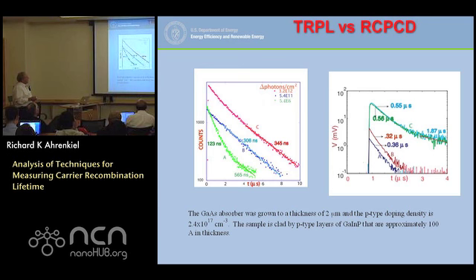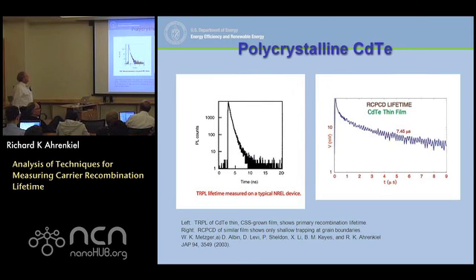Then we go to much higher injection and we get into other issues, related to mobility problems that I'll talk about later. So we get some distortion at higher injection level that shows up in photoconductivity. If we went to high enough injection level here, we would see a bimolecular decay, and we see a steepening at t equals 0. So there are all kinds of regimes here that will cause problems. But they basically agree: 300 nanoseconds is the lifetime that both measurements show.